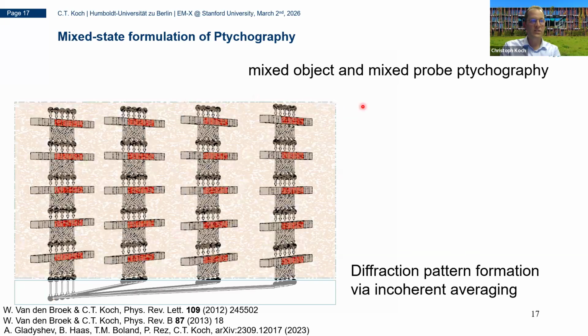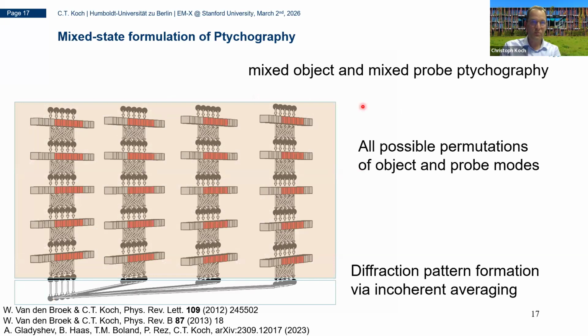Or what we do is actually have now multiple probe modes and multiple objects. So really accounting for both partial spatial coherence independent of the thermal diffuse scattering. And how is the thermal diffuse scattering implemented? Well, we first do a single object reconstruction until we get a decent reconstruction result. And then we make basically copies of this object, 20 copies, for example, and then add a little bit of random noise to each of these copies so that they're not the same. And then they can develop independently.